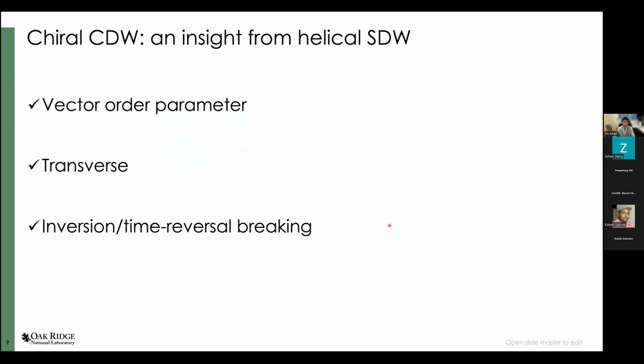In order to have a chiral density wave, first of all, you need a vector order parameter. Secondly, you want it to be transverse so that you can define your chirality. And finally, to have this order, you definitely need to break some symmetry, such as inversion symmetry or time reversal symmetry. But that gives a puzzle, because charge density is a scalar physical quantity. So actually, it makes no sense to say chiral charge density wave.